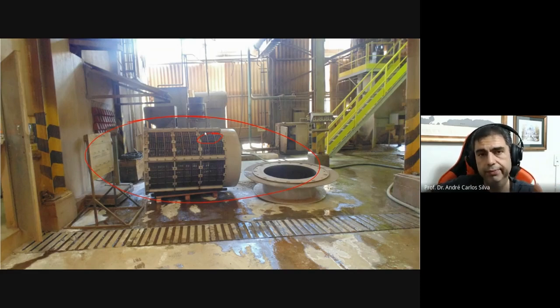we have a lot of organic material. Our material coming straight from the mine came with roots, even leaves and things like that. And we also have plastic contamination from the blasting, and we need to take those out. For our next stage, a comminution stage, we have a hydrocyclone first. So our closed circuit is not the first milling stage, but the second one. But instead of feeding our material directly to the second mill and from the mill to the hydrocyclones, we fed our material straight to the hydrocyclones because we have a lot of fines. So if we remove the trommel, I'm going to be putting in our hydrocyclones first organic matter, and second plastics.